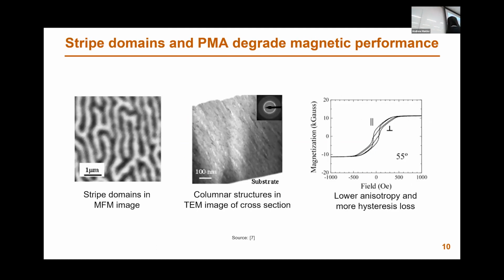And it's actually pretty easy to get MH loops that don't look like the previous slides, that have higher hysteresis loss. One way that causes that is if you grow films with a lot of PMA and stripe domains, which are kind of correlated. So if you ever see stripe domains in your MFM image, or column structures in your TEM image of these films, then typically the MH curves look like the ones on the right, where you don't have very strong anisotropy. You get a mixed behavior in both axes, which generally means that the loops look wider in both axes and equates to more hysteresis loss, which is generally what we don't want.